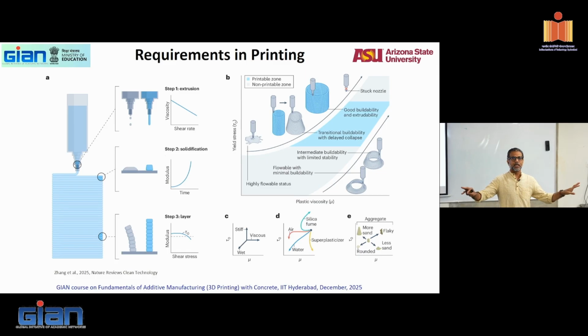but separate the cement grains farther apart. They do nothing but deflocculate the cement grains. They do not add extra water to the system. They cannot bring in more viscosity in any form or fashion. If you have to change the viscosity, you have to add a viscosity modifying admixture that changes the viscosity of the solution, that changes water to honey or honey to oil or whatever, right? Otherwise, superplasticizer simply spreads the cement paste farther apart, giving you an illusion that this is actually flowing better.